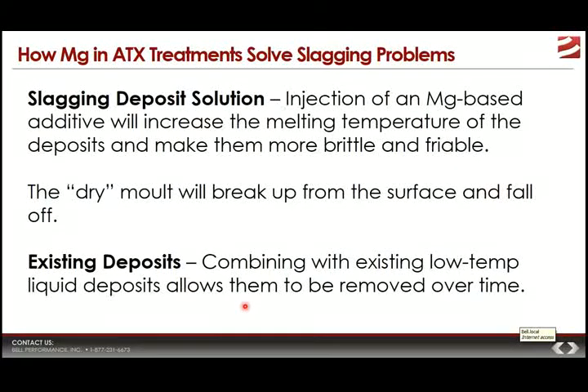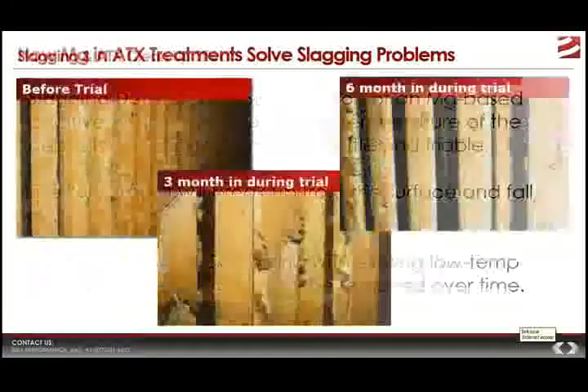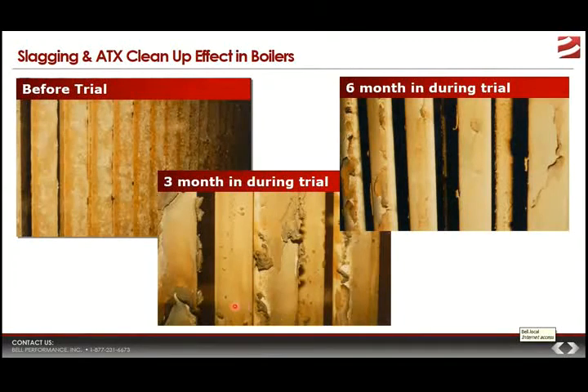Now, another thing that magnesium does is the oil-soluble magnesium actually attacks and penetrates existing low temperature deposits and helps remove them, which is a very significant benefit that you can't get with a conventional, let's say, magnesium oxide, which is not oil soluble. Now, this customer here, before their trial, these were some of their heat transfer tubes, and as you can see, they had significant deposit buildup on those. Three months into the trial of treating their fuel oil, you can see that those deposits are falling off. These tubes are significantly cleaner than these tubes. Six months into the trial, you can see that those tubes are clean. They might get a little bit cleaner, but they're very close to being back to what they should be.